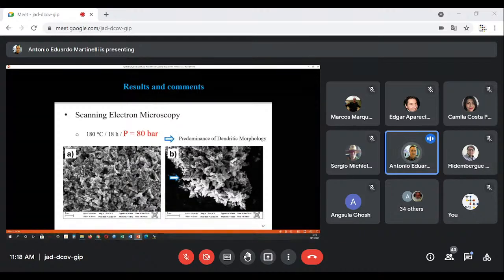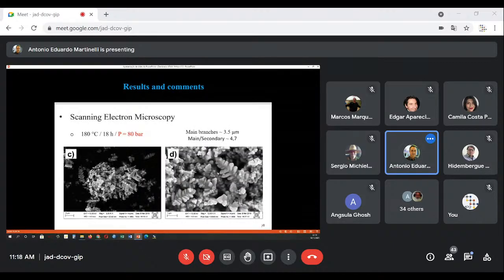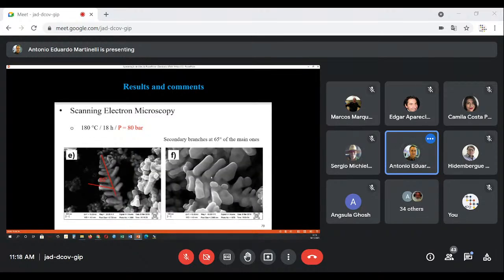Now 80 bar, and the powder is completely different from the powders that we obtain at lower pressures. We see here the flowers, and we could actually measure the main branches and the ratio between the main and the secondary branches of the flowers. We saw that the main branches are about 3.5 microns long, and the ratio between the main and secondary branches is about 4.7 times. Here are the secondary branches. We could measure the angle between them, and this is a close-up of this morphology.